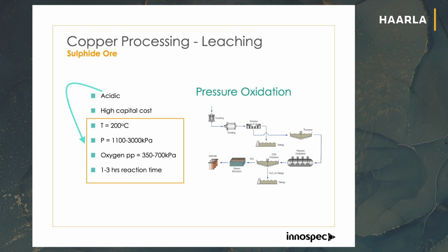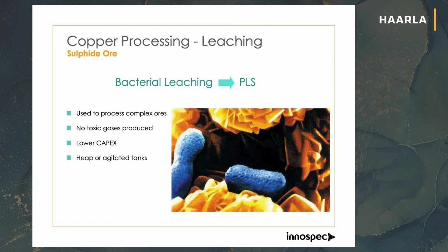One of the newer areas that you've got is copper processing using bacterial leaching. So bioleaching. And this is where you're using quite an intelligent way. You're using little bugs to go in there, and they're attacking the ferrous sulfate and converting that ferrous sulfate into ferric sulfate, and getting the sulfuric acid produced. The ferric iron is a very strong oxidizing agent, as you know, which then oxidizes the copper, and the sulfuric acid then dissolves the copper and takes you into the solvent extraction and the electrowinning process.